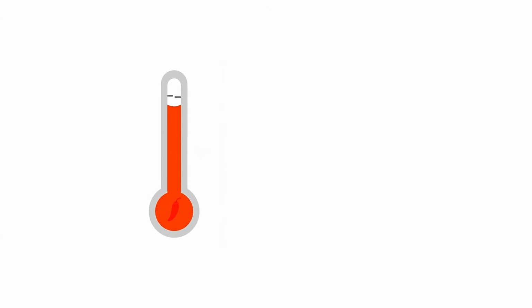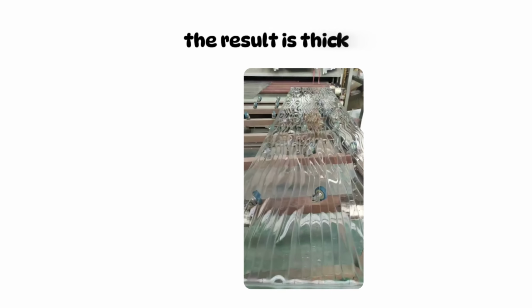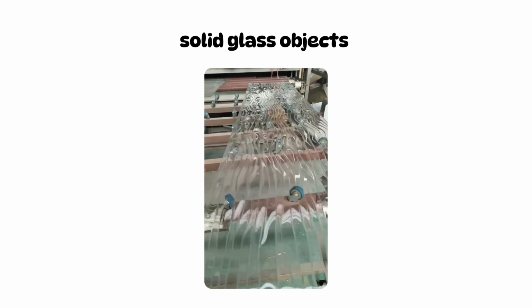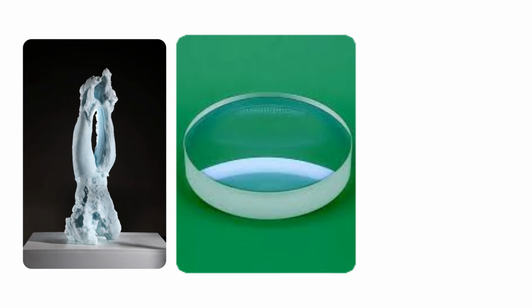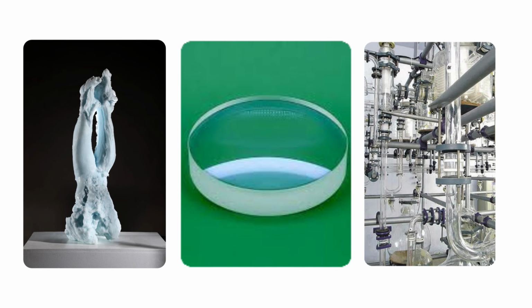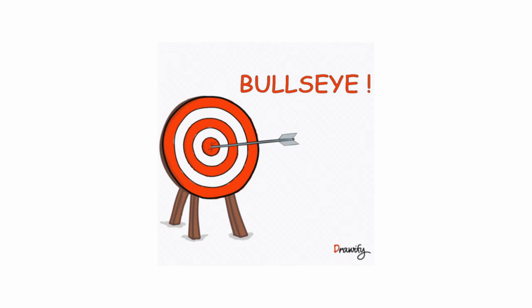So the cooling has to be controlled extremely slowly in a process called annealing. Temperature drops gradually, sometimes just a few degrees per hour. This allows internal stress to release safely. The result is thick, solid glass objects that can't be made any other way. Sculptures, optical lenses, industrial components, anything that requires depth and strength. It's one of the most time-consuming methods, but also one of the most precise, because once it's poured, there's no going back.